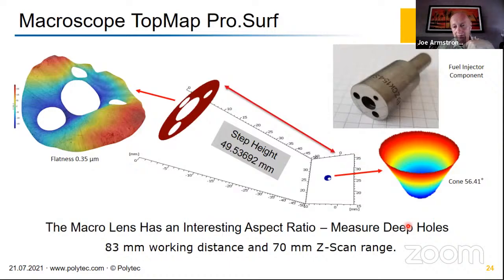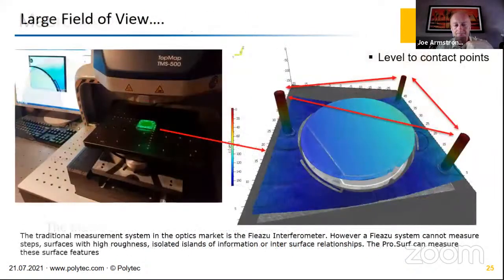It's specifically designed for flatness. You can get some cone angle measurements. And here I have a measurement where I'm measuring down a hole, which is almost 50mm, and we can measure that. Really different behavior to that of a microscope type system. And I think this image here really sums up that capability quite well.